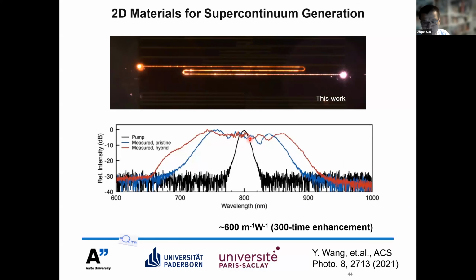We measured the spectrum. The black one is the input spectrum. The blue one is the spectrum without the 2D materials transferred on top of the waveguide, and the red curve is the result after transferring the 2D materials on top of the waveguide. You can clearly see that with the integration of the 2D materials on top of the waveguide, we could get a much broader spectrum. This is because the 2D materials could enhance the nonlinear coefficient of the silicon nitride waveguide.